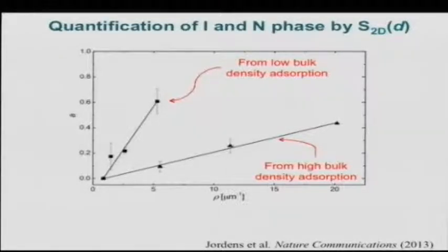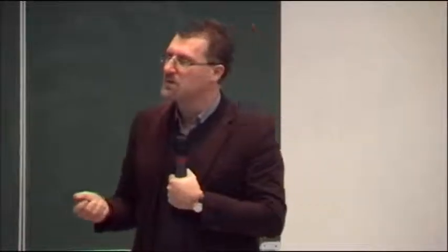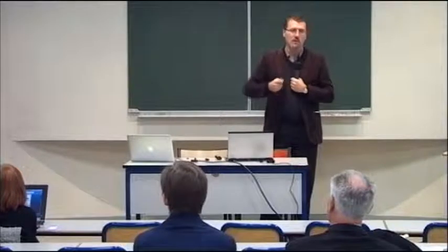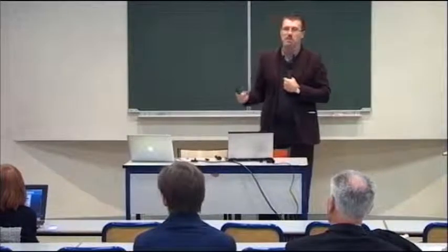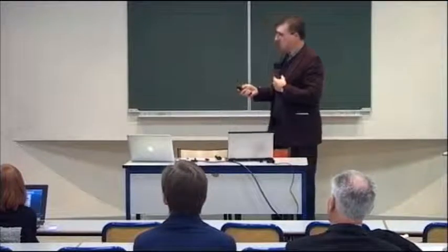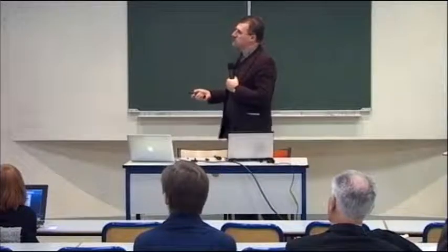And now we do understand why the isotropic-nematic transition in 2D has been debated for more than 30 years, because this is the signature of a non-equilibrium phenomenon. So non-equilibrium phenomena do dominate this kind of behavior. So observing isotropic and nematic coexisting in 2D does not allow you to say unambiguously whether this is a first or second order transition.